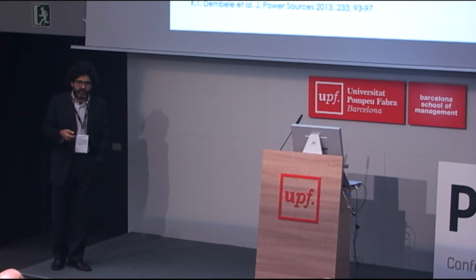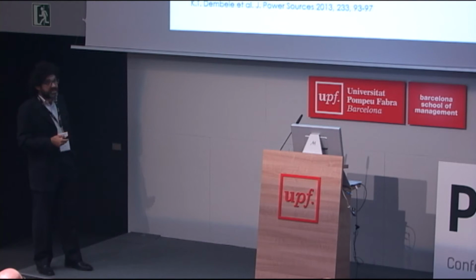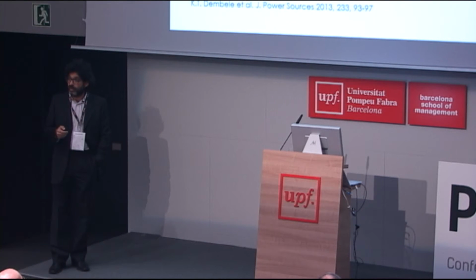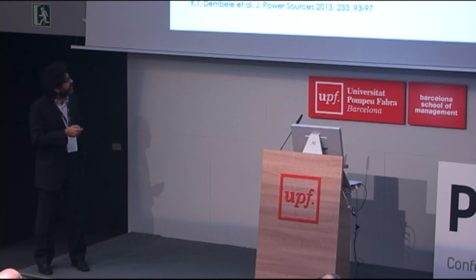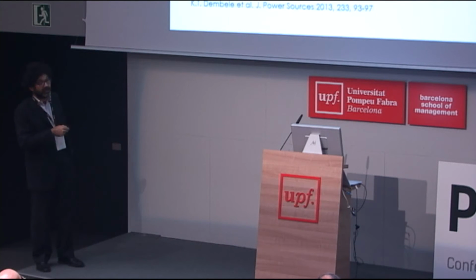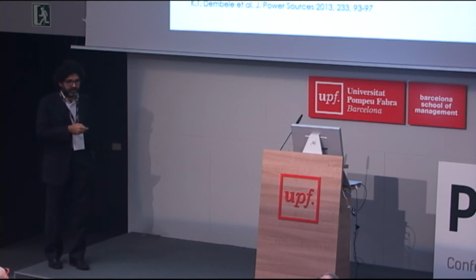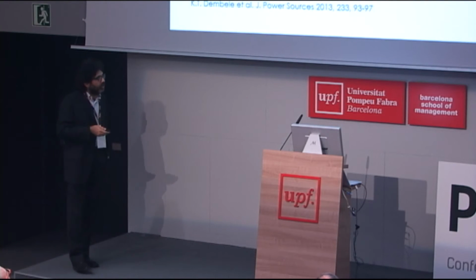What's the difference compared to Kamat's work? It's exactly the concentration of carbon nanotubes you have in your system. In fact, the maximum efficiency is just for 0.01 in weight carbon nanotubes in titanium oxide. If you look at the previous results, they were employing much higher concentration of carbon materials, and in that case you lose all the beneficial effect of carbon materials in boosting the functional properties of the device.